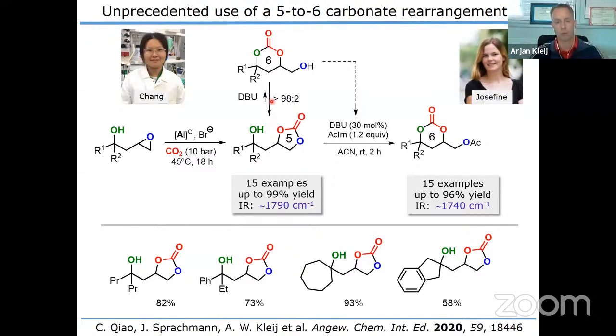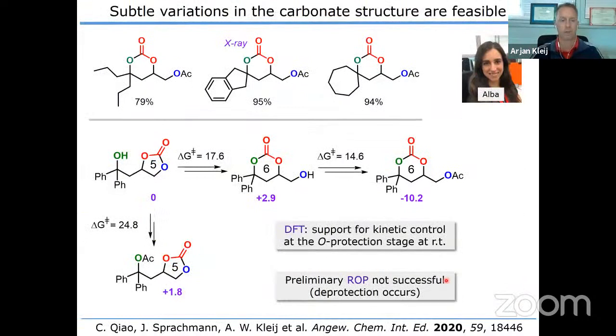However, we do know that this equilibrium exists because once we get to this stage, we can acylate, of course, this primary alcohol, and we can drive the equilibrium to the protected 6-membered compound. So we made use of a number of these 5-membered cyclic carbonates, and we can then also produce their respective 6-membered cyclic carbonates. And this is, I think, one of the few methods where you can go from a 5-membered to a 6-membered ring product. So this is quite unusual.